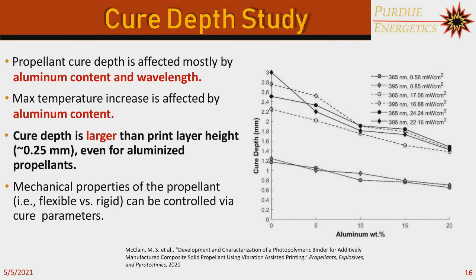Slide 16. Here on the right is the main result of our study, although we did many other tests. We showed that as we increase aluminum content, we're still able to cure relatively deeply with this photopolymer mixture, about 1 to 3 millimeters. That's good for us because when we 3D print a layer, we typically print at about 0.25 or 0.3 millimeters. If our cure depth was less than that, our printed layer would have uncured regions in it, and that is just not desirable.